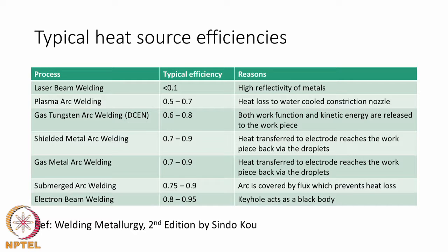And then comes the plasma arc welding, which has an absorptivity between 0.5 and 0.7. The reason why plasma arc welding is slightly on the lower side of the efficiency is because there is a water cooled constriction nozzle that is surrounding the plasma jet, which is present in the plasma torch. Because some of the heat is lost to this water cooling jacket surrounding the plasma torch, the efficiency is slightly on the lower side.